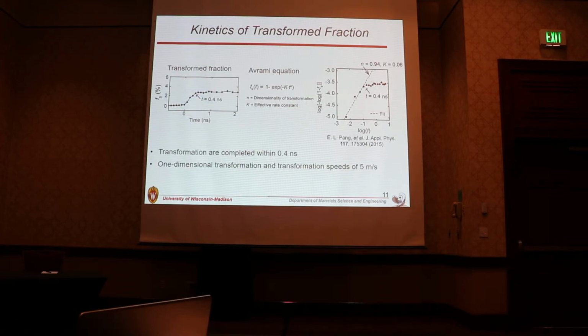So we studied the kinetics of transformation by obtaining the transformed fraction as a function of time, and we found that at 0.4 nanoseconds after the optical excitation, about 3% of the fraction of the film is transformed, and the transformation process is almost done at 0.4 nanoseconds. So we use the Avrami equation to understand this. We can study the dimensionality of the transformation and also the growth rate. Because the transformation process is done within 0.4 nanoseconds, we use the data obtained within that time, and we fit the Avrami equation and found that the dimensionality equals 0.94 and the rate constant equals 0.06.